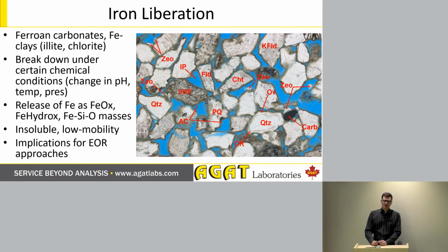Iron liberation is a potentially serious concern. A lot of these sands have ferroan carbonate as a cementing agent, and what we end up with is, if we start to dissolve away these cements, the iron is liberated and becomes a kind of gel-like obstruction and is very, very difficult to get rid of. It can basically occur as iron oxides, iron oxyhydroxides, and these strange iron-silicon-oxygen kind of masses which are amorphous. These are very insoluble, so you can't really redissolve them, and they are low mobility as well.